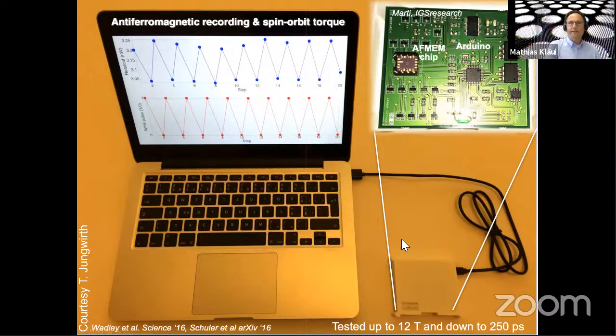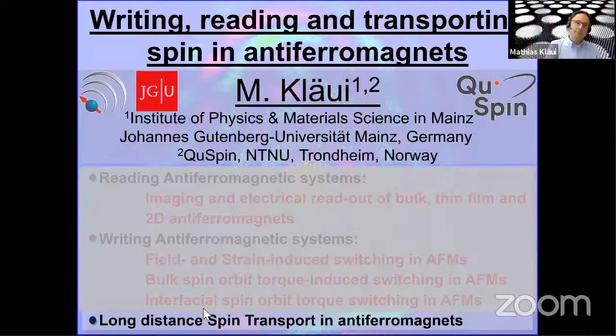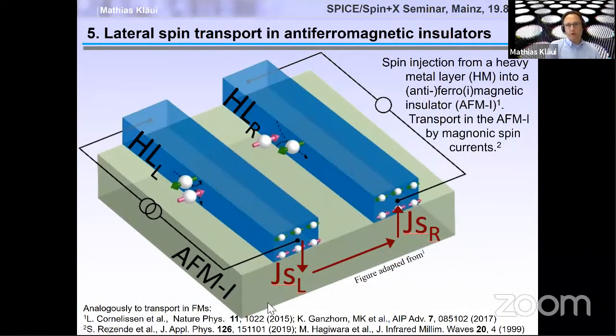And now in the last 5 minutes, let me just give you a few updates on spin transport in antiferromagnets. So if you have an antiferromagnet and you'd like to transport spin, the typical geometry that you're using is a so-called non-local spin valve. So in such a non-local spin valve, we have our spin conduit, which in our case is an antiferromagnetic insulator. We have two lines here, which are platinum, which is used as a spin injector due to the spin Hall effect, and the spin detector due to the inverse spin Hall effect. And this was pioneered for ferromagnets by Bart van Wees in this paper by Ludo Cornelissen. And then this was extended to antiferromagnets.